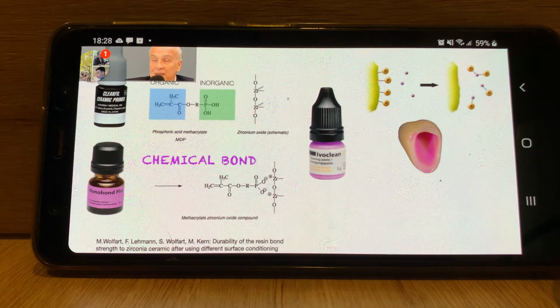Now, we talked about cleaning. Why do you need to clean the surface? Why can't you just put the MDP directly on the surface? Well, because if you've tried it in the mouth, the saliva or blood, whatever got on there, has phosphate groups in it, usually in the form of phospholipids. And these phosphate groups are now occupying the binding sites, and your primer cannot get to them. So we have inadequate bonding.